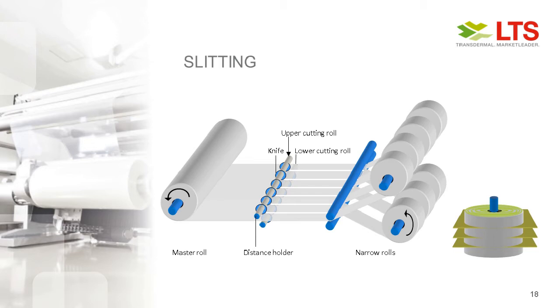In the next step, we go to slitting. Here we slit the master roll with scissor-type knives down to narrow rolls. These narrow rolls are already predetermined in their width by the product size. They can be stored, as you can see, horizontally, and stacked pretty easily before they go into conversion, whereas the master rolls are pretty heavy by their own weight to store, so the narrow rolls are really preferred for that.